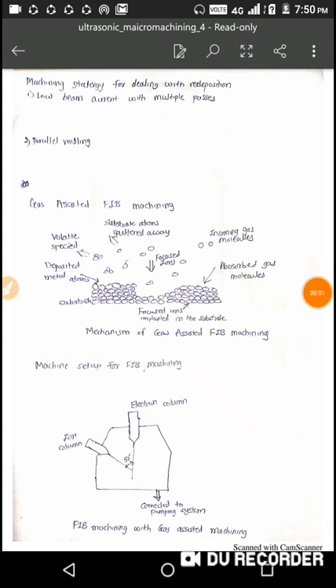Well, there are generally two strategies used to deal with this undesired effect, that is redeposition. Generally, if we increase the sputtering rate, there are chances that the redeposition rate will also increase. But if we use low beam current, then it will decrease the machining rate. So to maintain a high material removal rate, an ion beam with low current makes faster repetitive passes with a faster pattern instead of a slow single pass with high beam current. It is used so that we can avoid the redeposition effect.